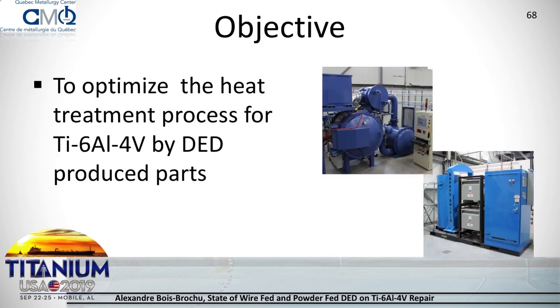The second objective is to optimize the heat treatment process for TI64 parts produced by DED. All the heat treatments that we used within this project were based on existing heat treatments within standards. The purpose of that is that clients using the results can directly use those heat treatments to produce parts afterward. Why do we need to optimize heat treatment if they already exist? It is that, as you will be able to see, the standard heat treatment proposed in some standards results in mechanical properties that are below the actual requirement from the same standard.